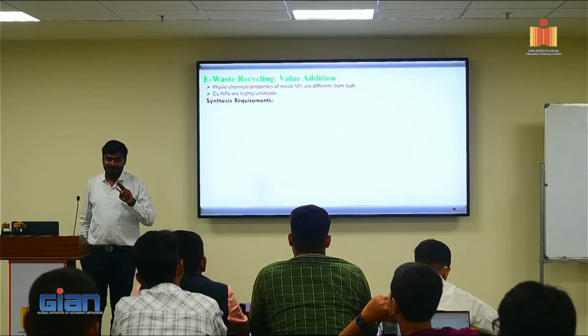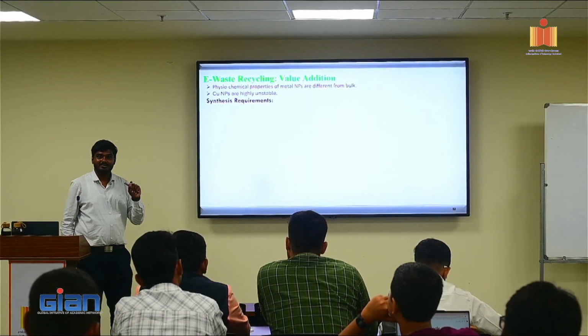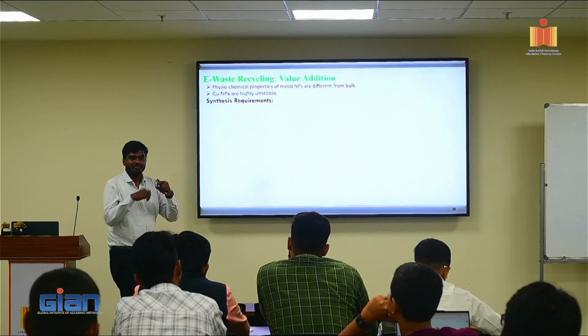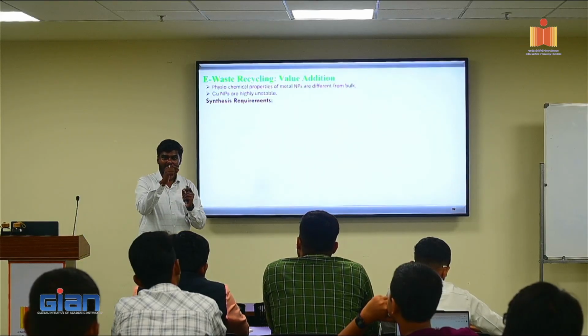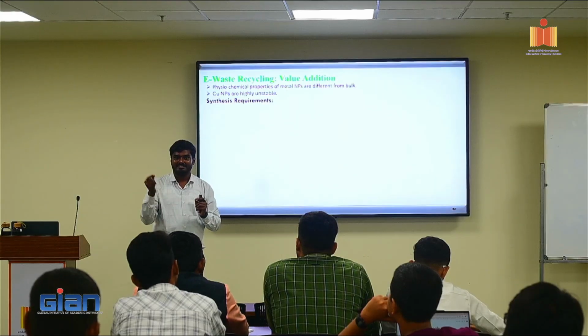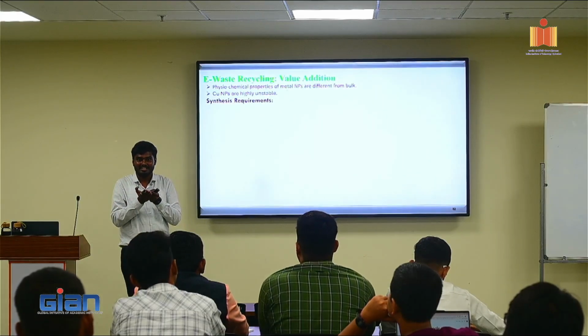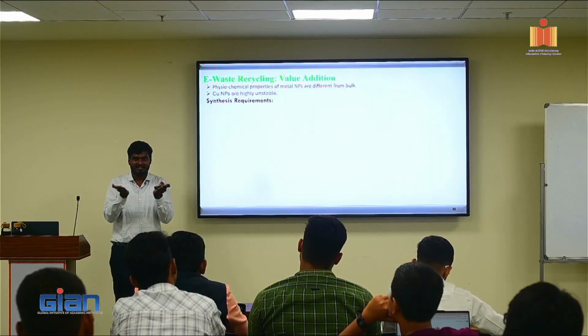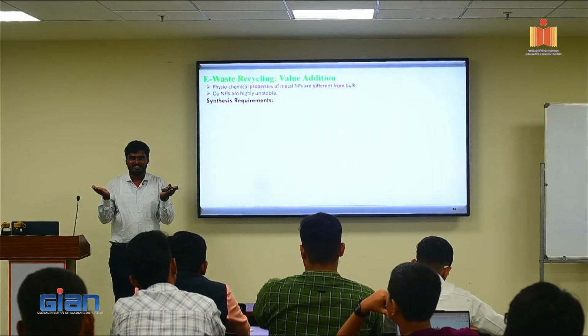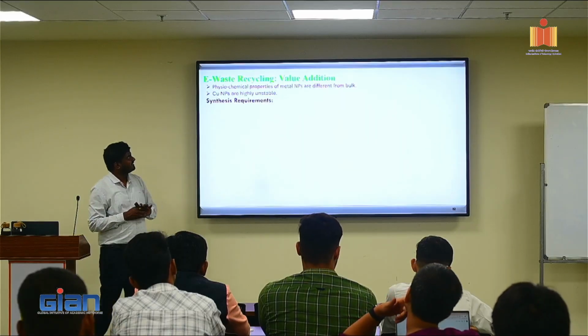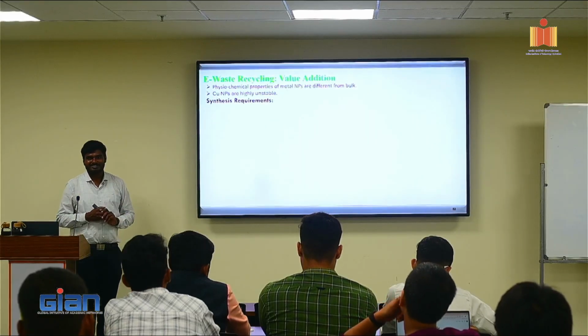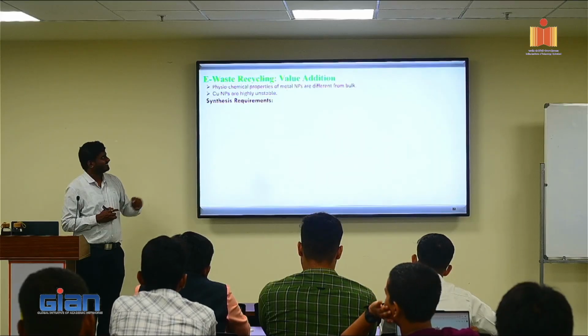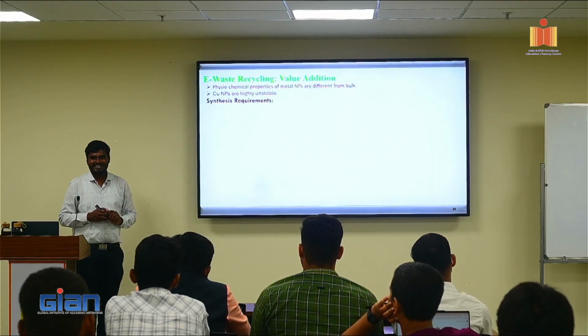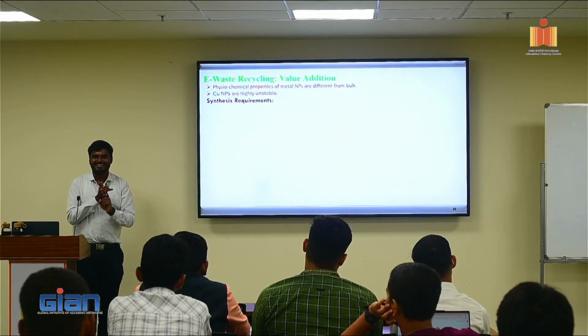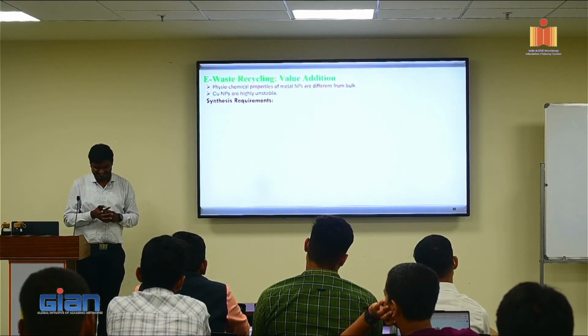But we need pure copper because this copper is used in conductive inks. So if you want to make any flexible electronics and conductive patterns, these nanoparticles are dispersed in these inks and they heat it such that it will melt and form a thin conductive layer. So our idea was to develop a process to convert copper nitrate to copper nanoparticles. And these copper nanoparticles are highly unstable. Now I have to do a literature survey again from scratch and address these things.